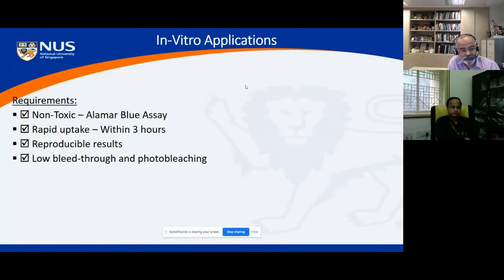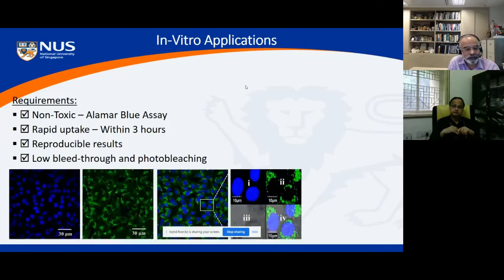Yeah. So let me show you a few glimpses because I don't think I have a lot of time to go through it. For the cellular model, we make sure that these polymer particles are not toxic, you know, that means we don't put too much, and also we don't use very toxic chemicals to start with, right? And the biological cells should be able to take these things in a reasonable time, right? 3 hours to a couple of days, not too long to expose. And we must get reproducible results. So many studies reported in the literature are kind of difficult to follow because some of the data is not clear enough, right? Low bleed through, photobleaching. Your dye should be able to stay during the imaging process. It should not get shut off, right? Or it should not lose its properties.